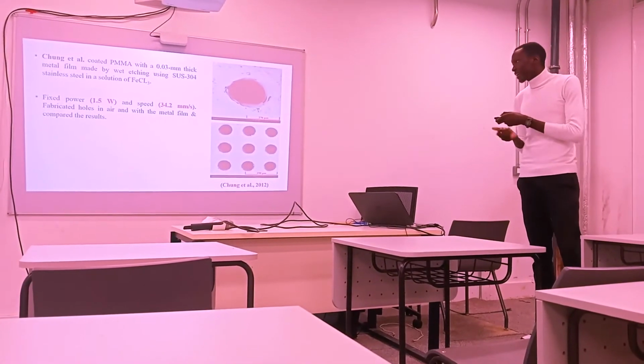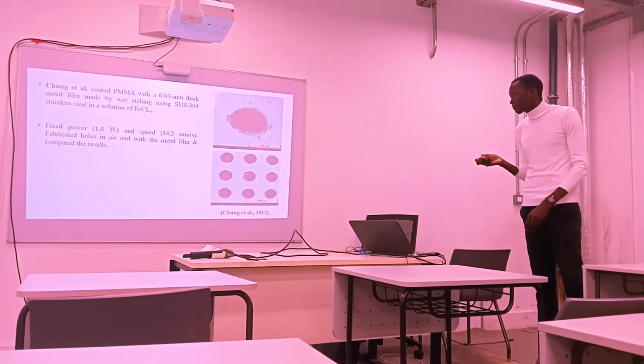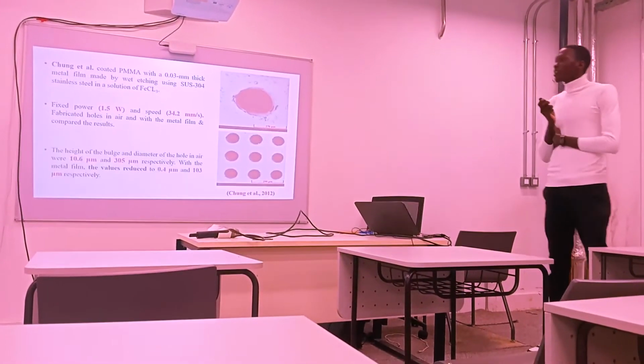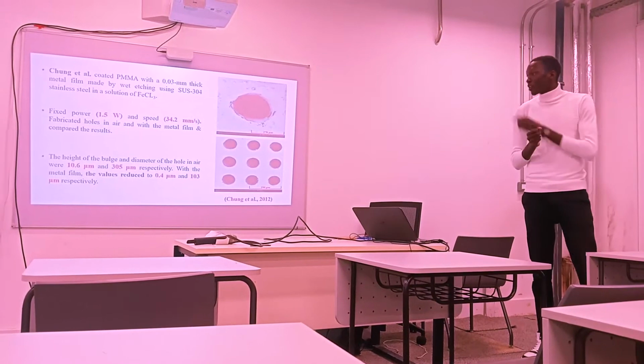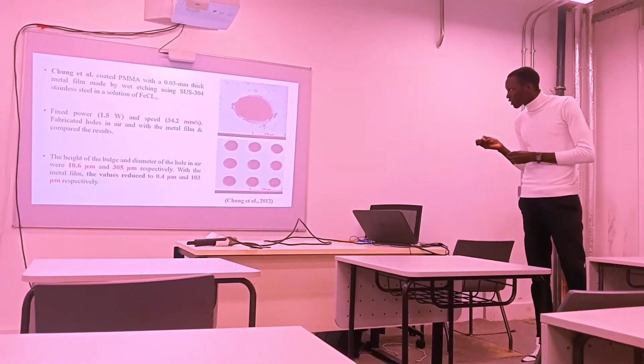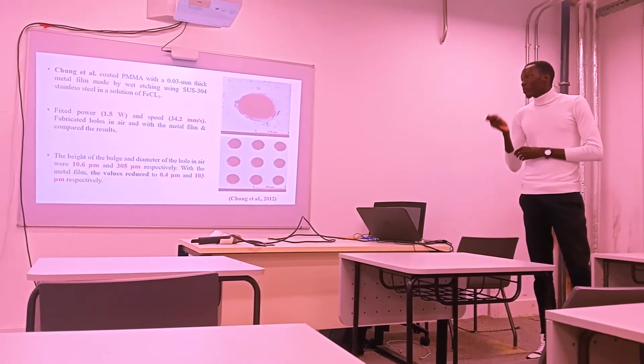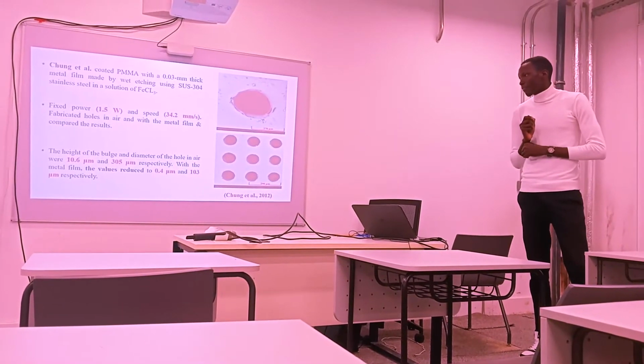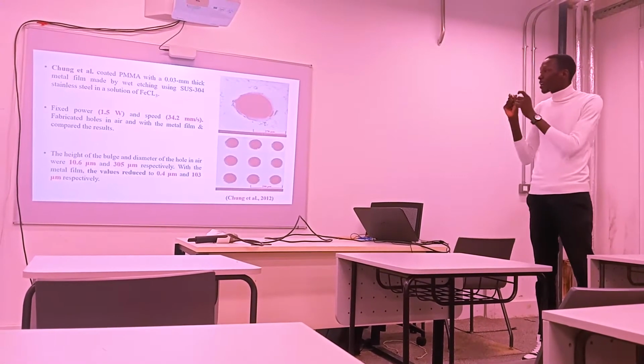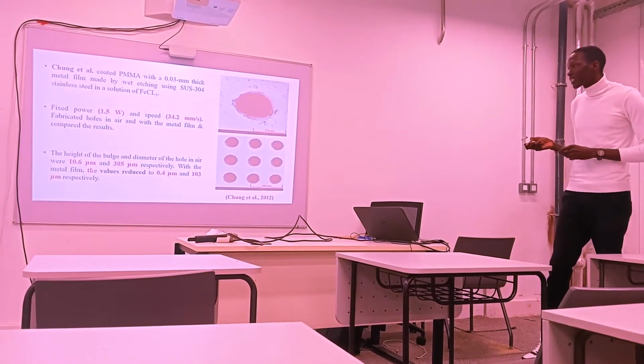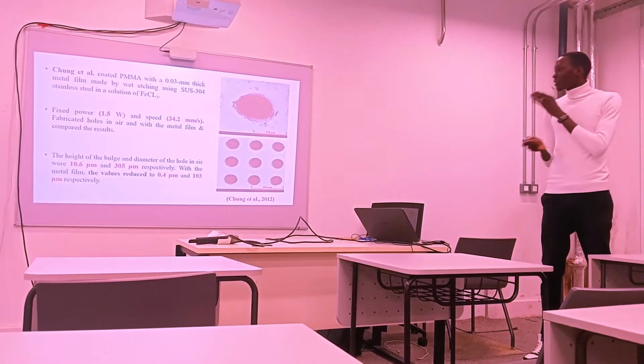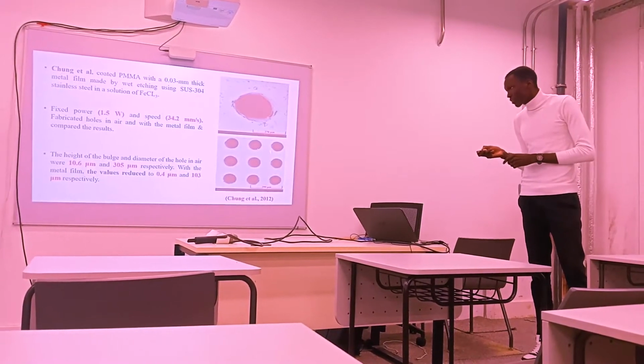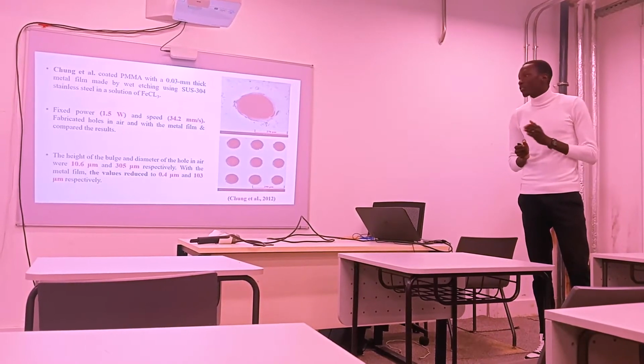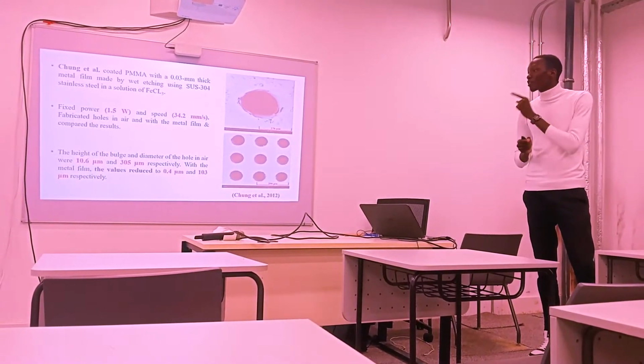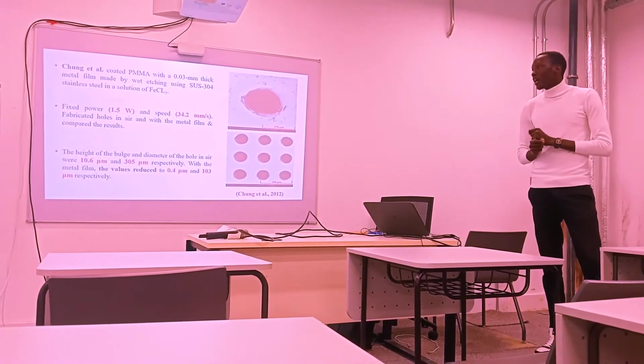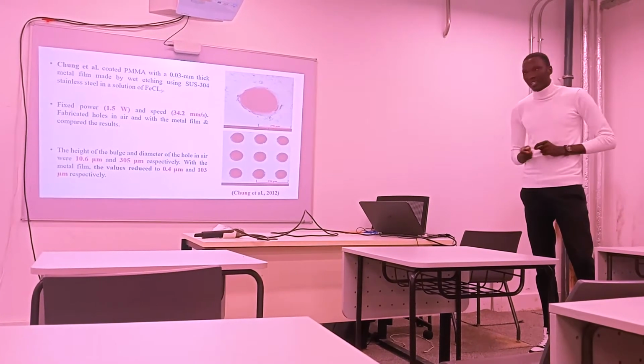This is in air, and this is with the metal film. They found the height of the bulge and the diameter of the hole in air. The diameter of this hole in air was 305 micrometers, and the height of the bulge was 10.6 micrometers. With the metal film, this is what they found: the values reduced. The height of the bulge became 0.4 micrometers, and the diameter became 103 micrometers.